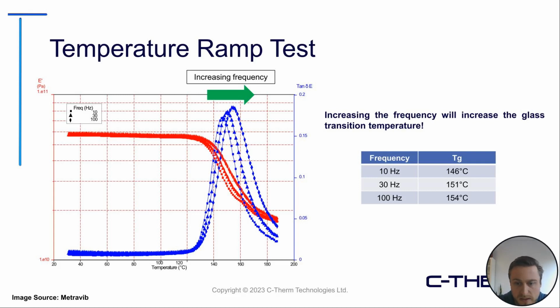From this plot here, we can see this effect where a temperature ramp test was done from about 30 degrees up to 190 at a set temperature rate while exciting the material at 3 different frequencies. What we can see here is that the machine was able to recognize differences in material performance under each condition, under each frequency.